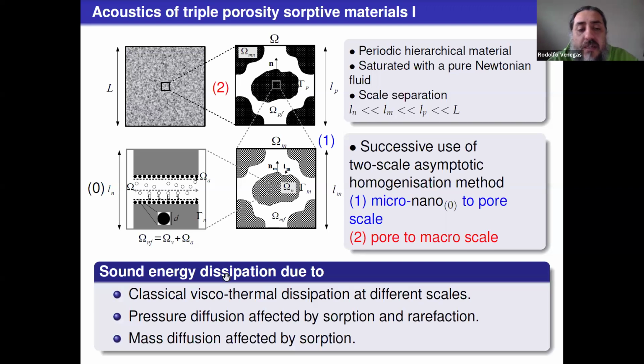What characterizes these materials in terms of sound energy dissipation is that we have classical viscothermal dissipation at different scales, at the scale of the grains and at the scale of these macropores, and also we have pressure diffusion interacting between this scale and that scale, and that's affected by sorption and rarefaction. Rarefaction happens in very small pores, and sorption mainly happens in nanopores. And also we have mass diffusion affected by sorption. I will explain in more detail what these diffusion processes are along the way.